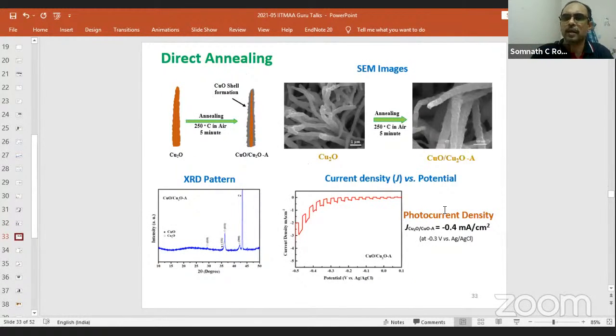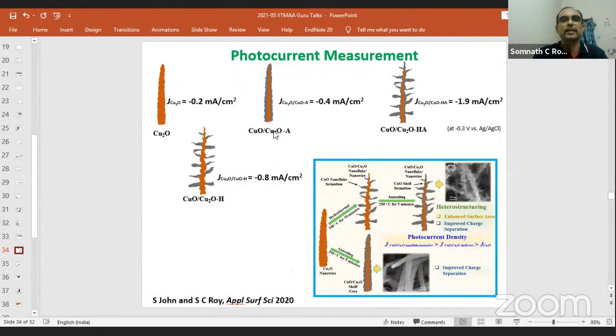So we ran every possible scenario. We found that, of course, Cu2O, CuO helps, but we wanted to check whether these nanoscale 3-dimensional structures are helping anyway. For that, we skipped the step of this flake formation. We just had a simple thermal processing where over Cu2O, as you can see the top left, we had done a coating of CuO, simply a coating, no flake type, needle type structure. Here also we found an increase in current, but it is only double, 2 times increase, not 10 times. Which means that in this kind of structure, it is both the Cu2O, CuO heterostructure that is helping, as well as these nanoscale branches from this vertical basic structure.